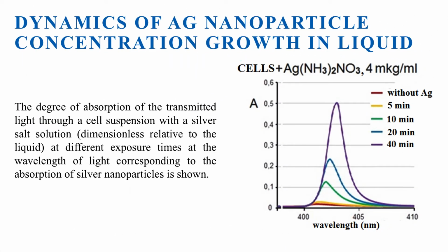The dynamics of silver nanoparticle concentration growth in liquid was studied. It was found that over time the absorption of light increases at wavelengths typical for silver nanoparticles, which makes it possible to conclude that the concentration of nanoparticles increases over time.